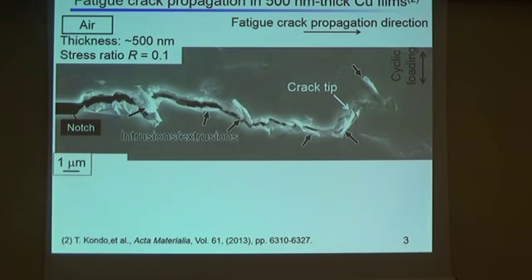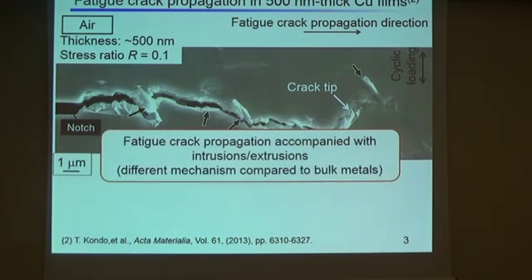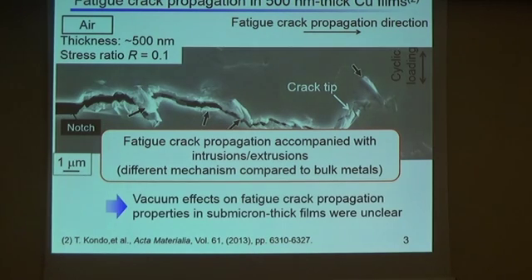So, in the thin film specimen, fatigue crack propagation accompanied intrusions and extrusions. And this mechanism is different compared to bulk metals, that is, crack tip blunting and resharpening. So, because of these differences, the vacuum effects on fatigue crack propagation properties in submicron thick films were unclear.